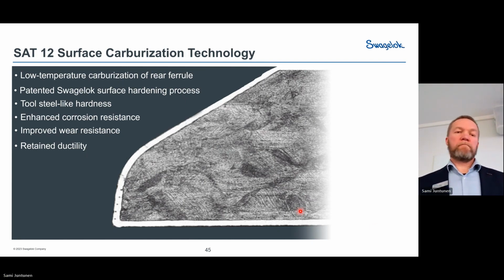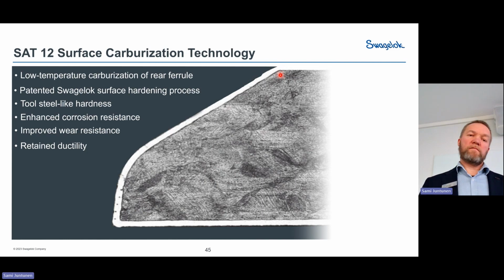And in here, Swagelok has a unique low temperature carburization process where we get a very hard surface over the back ferrule. At the same time, even though the surface is very hard, the inside of the ferrule, the material, is the same. It's 316L, and that means that we will not sacrifice any corrosion resistance, but the material is very ductile, so it's non-brittle. It will not crack during installation.